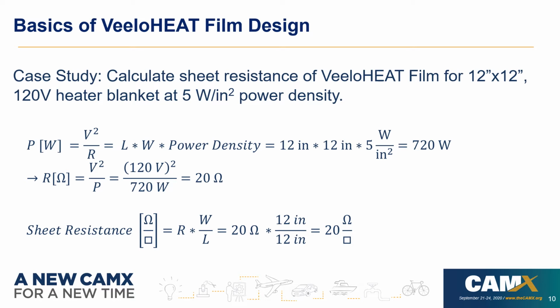So power, as you know, is voltage squared divided by resistance, and then this would be equal to the length times the width times the power density of the heated area. So for a case study for a 12 by 12 inch heater at a standard 5 watts per square inch, this ends up being 720 watts. So solving for resistance, we end up here with 20 ohms.